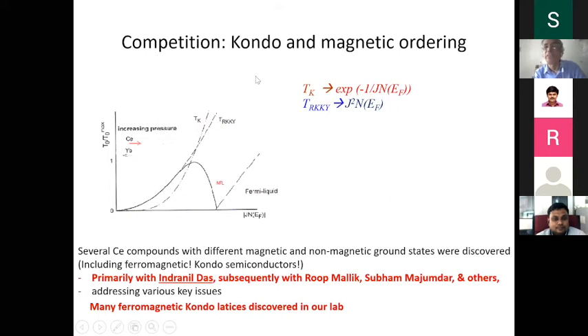Therefore, for example in cerium metal or in many materials, you start with the magnetic material, apply pressure or change concentration, you go through the peak of the magnetic ordering temperature and it suddenly comes down. At this point you lose magnetism, and you find what is called Fermi liquid behavior. In this region you see a strong valence transition. Here you have a weak valence transition or no valence transition. There are plenty of very exotic features in this phase diagram. I just want to inform you that today people are playing around with this phase diagram. Depending on the material you choose, many exotic anomalies are found.